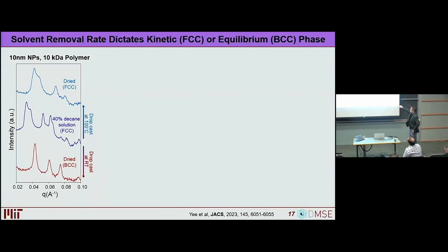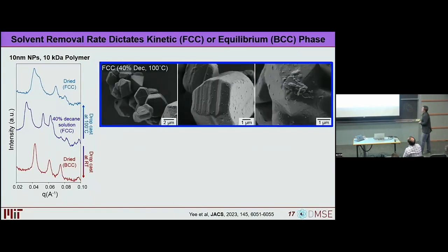The BCC case we can look at very easily by just following our standard protocol of transitioning to decane and then drying that out. To get the FCC case, he found that if you could drop cast these materials at 100 degrees C, you can basically flash boil off all of the decane. This doesn't give the particles time to reorganize, and so we can retain that FCC case even in the dried state.